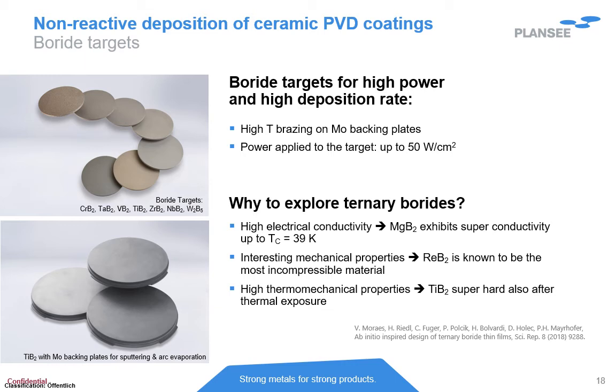The question is, why explore ternary diborides? I think these materials have big potential for certain applications as they show a huge range of interesting properties. For instance, magnesium diboride is a superconductive material up to about 40 Kelvin. Rhenium diboride is known to be the most incompressible material. Titanium diboride is well known and established because of high hardness and not too bad thermal stability. Many researchers are working on these materials already, discovering new possibilities and maybe also new application fields.